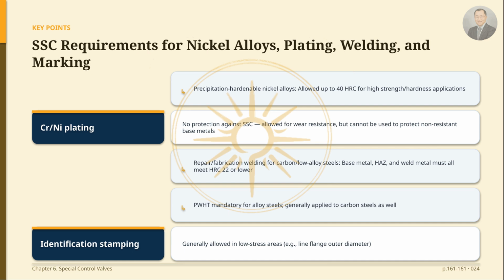base material from SSC. Weld repairs and fabrication welds on carbon and low-alloy steels must be properly processed to ensure that the base metal, the heat-affected zone, HAZ, and the weld deposit all meet the maximum hardness requirement of 22 HRC or less. Post-weld heat treatment, or PWHT, is mandatory for alloy steels and is generally applied to carbon steels as well. For identification marking, conventional stamping is permissible in low-stress areas, such as on the outside diameter of line flanges.